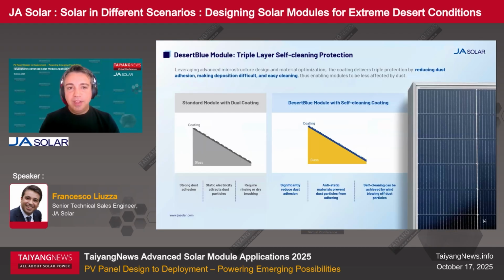Let's have a look at a maybe very impressive effect on dust accumulation due to the innovation on the glass. The glass has a specific microstructure design and specific coating. Here there's a picture. I will show you an animation. On the left side, the standard models with dual coating can have strong dust adhesion, and static electricity that can attract and keep dust particles, and require rinsing and dry brushing. The new glass applied on the DesertBlue significantly reduces dust adhesion, as anti-static material prevents dust particles from adhering, and self-cleaning can be achieved by wind blowing off the dust particles.